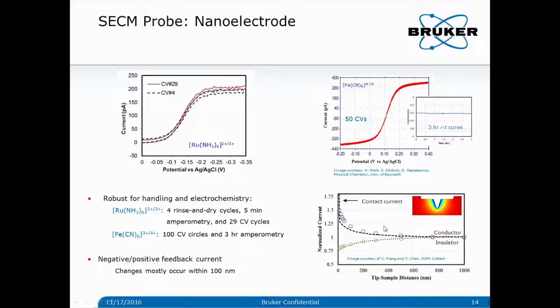More importantly, we can see that the change of the tip current occurs mostly within 100 nanometers of tip-sample distance. This is because the thickness of the diffusion layer is less than 100 nanometers. Such a compact diffusion layer and the high spatial sensitivity of this approach curve guarantee sub-100 nanometer resolution in EC imaging.